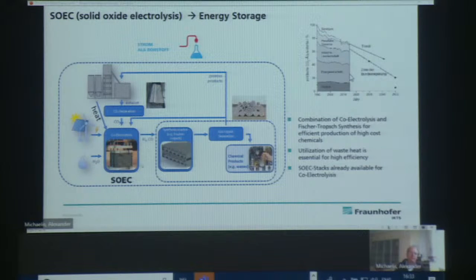system, electrolysis. And the beauty about this SOEC technology is it can not only convert water into hydrogen, it also can electrolyze CO2 into CO. So you also can electrolyze, so to say, CO2 from air into CO. And you can do this together, and this is then called co-electrolysis. So basically, you can actively remove CO2 from the air and then in one step produce this syngas, H2CO. This syngas then can be used to make all kinds of e-fuels or higher added value products, which I will mention later, for example, by Fischer-Tropsch technologies that we also implement. So it's a very nice technology for hydrogen economy and also for CO2 reduction.